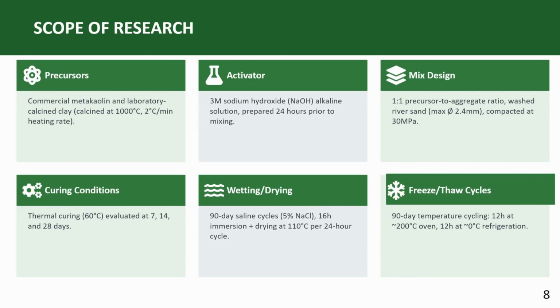The activator, or the alkaline, that was used was sodium hydroxide, and usually you have to prepare it 24 hours prior to the mixing. Then the mix design is that we used one part of the precursor, i.e. the calcined clay, to one part of the sand, that's the fine aggregate.